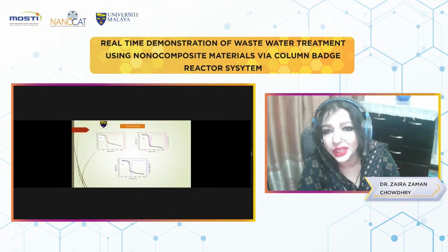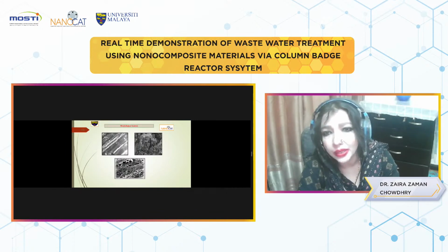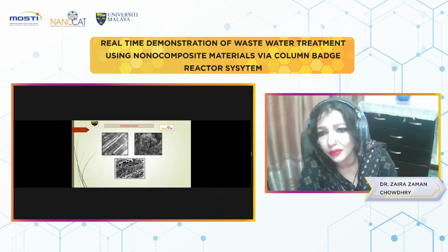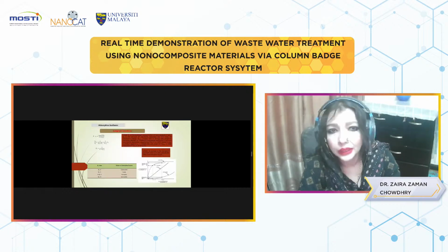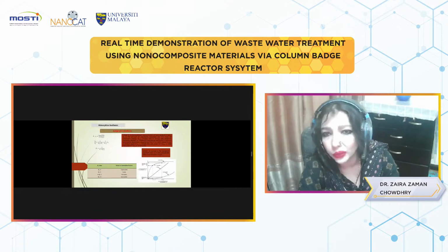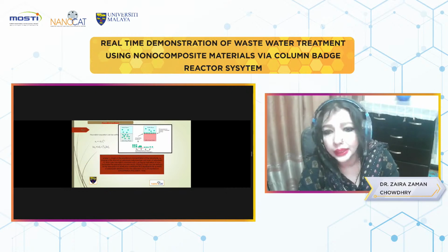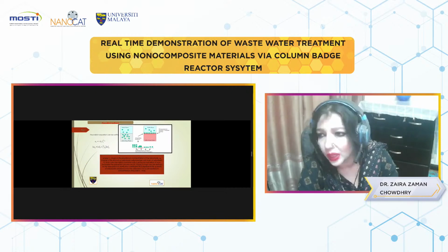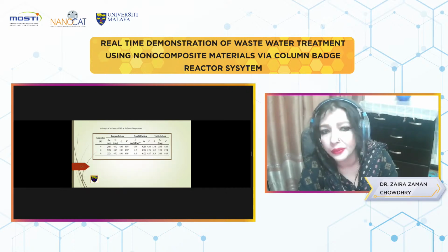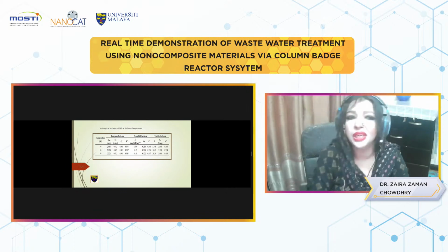This is our surface. We can see after hydrothermal carbonization, there was globular carbon form, but after activation, there were a lot of pores available over the surface, which can catch the copper pollutant from water. This is the Langmuir isotherm. We have used this equation. This is the Freundlich isotherm. We have used this equation and the Temkin equation also, and we ran this experiment at 3 temperatures, 30, 50, and 70.